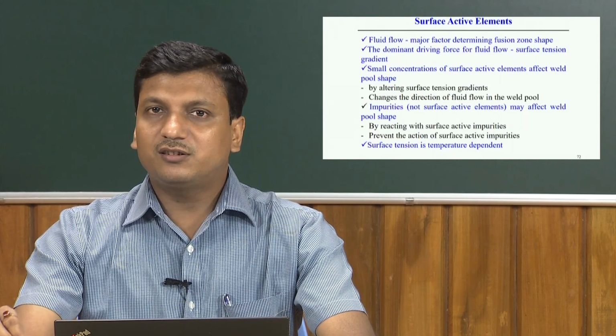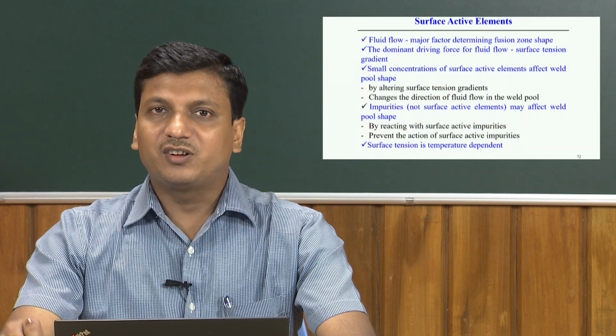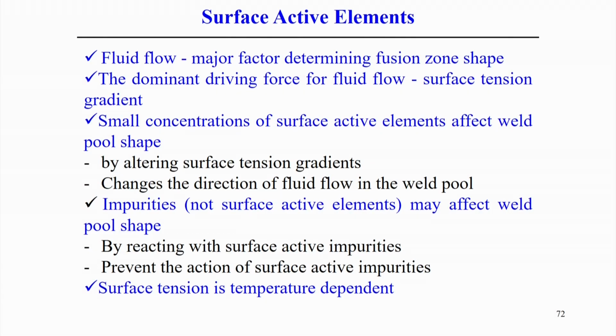But in the composition, there may be some impurities which are not surface active elements that may affect the weld pool shape in the way that impurities can react with the surface active element and form some other compound, and that compound can prevent the action of the surface active element by simply changing its concentration. So, that way it may be a complex phenomenon, but if we try to analyze the effect of the surface active elements, we consider that it is a binary alloy system.